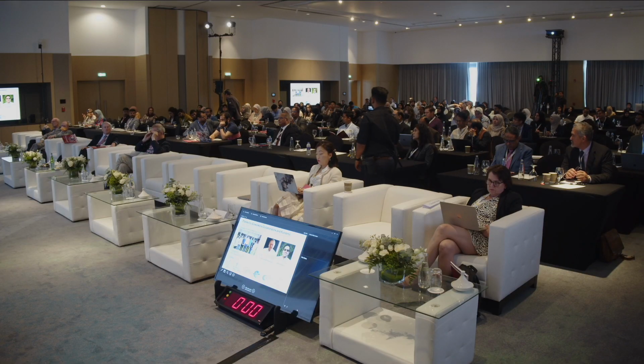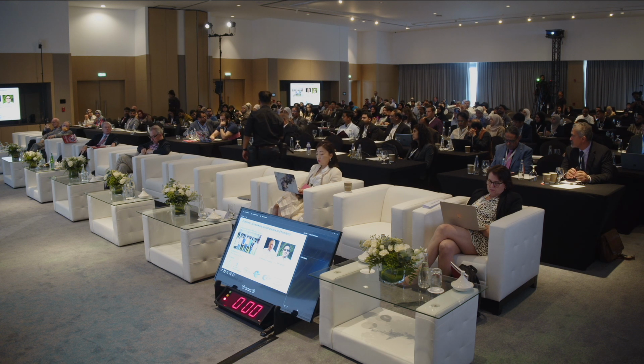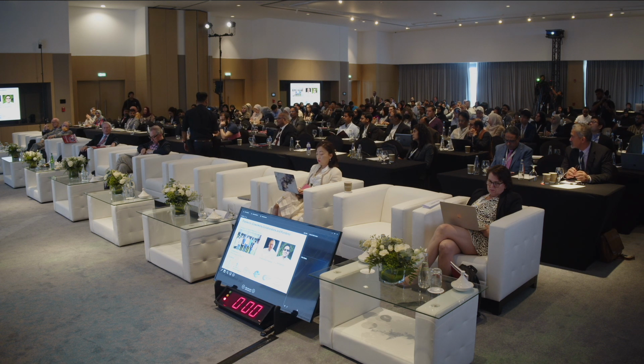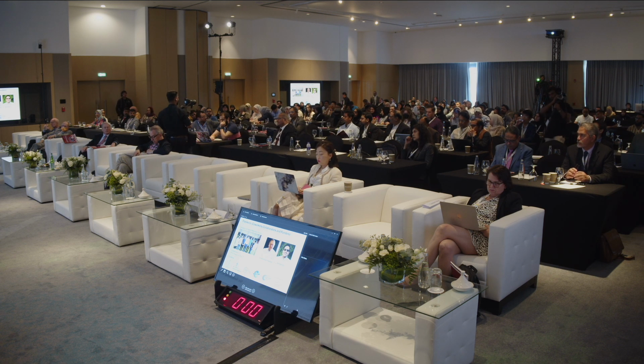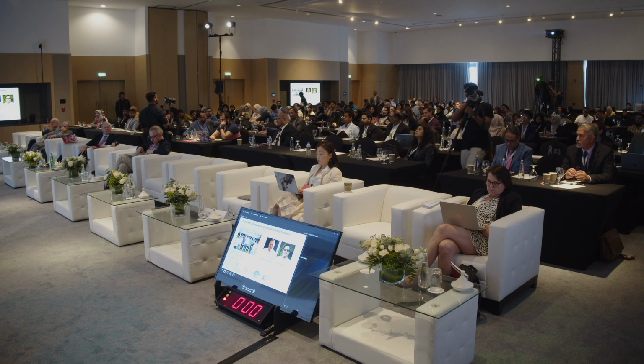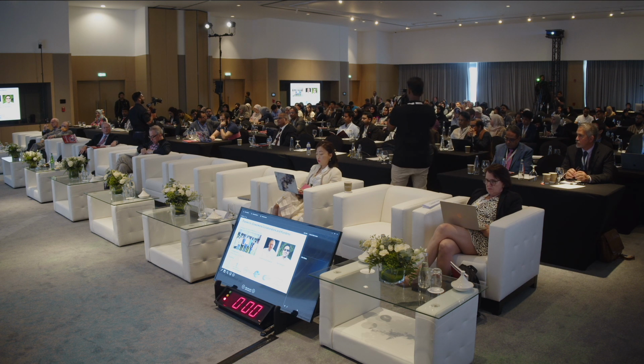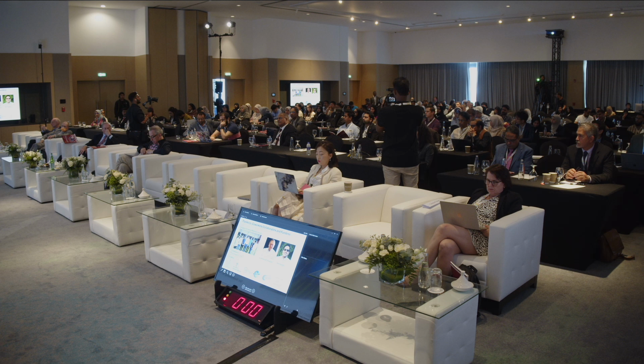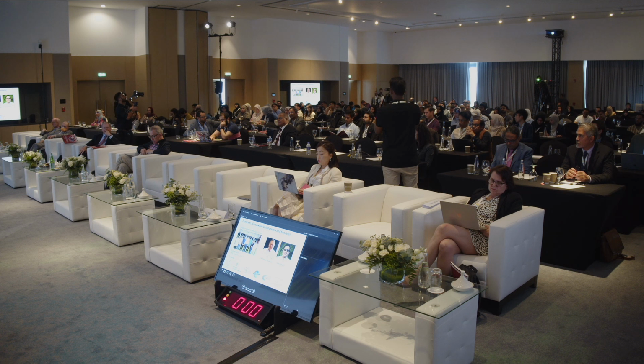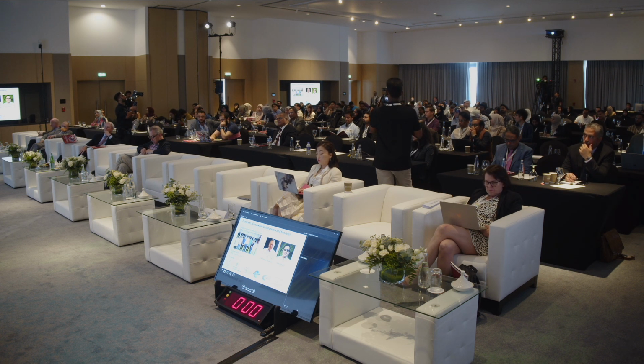Pratap, two short questions, comments. One with respect to the chlorine-bromine substitution, where you found that the bromine has a higher transition temperature. I would think that is to be expected because bromine will have a much stronger covalency. The hopping strength will be larger, and the J goes as t squared over U. So if t increases, the coupling strength should increase. So that's one thing. Yes, thank you.